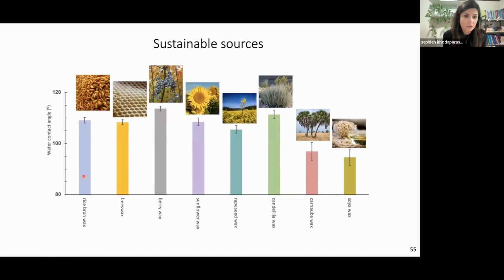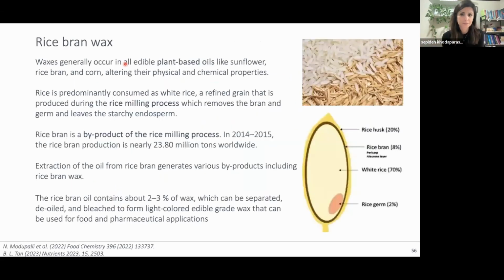I'm going to pick one of these, but we tried this technique for a majority of these waxes in this graph. The only thing you need to look at in this graph is that these waxes are typically hydrophobic materials, but the contact angle that you're looking at is the contact angle on a smooth layer of these waxes. And with a smooth surface, you can hardly get to above 110 degrees of water contact angle. To be able to get to angles such as 150, you really need to add surface roughness. Okay, so I'm going to use rice bran wax in the next few slides.